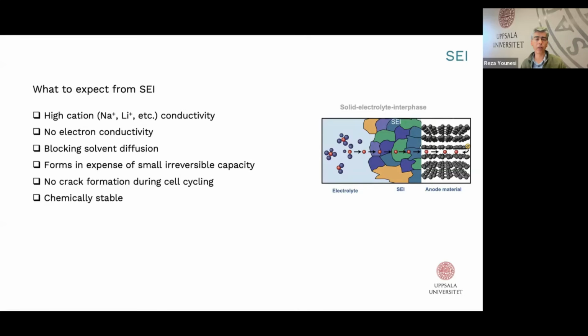It is expected that this SEI remains intact, with no decomposition over the lifetime of the battery at different conditions, temperatures, and cycling rates. Because if the SEI decomposes, a new layer forms at the expense of charge and electrolyte consumption, leading to aging and capacity fading. Ideally, we form SEI at the factory during the first few formation cycles with very little irreversible capacity, and that SEI remains stable and intact over the lifetime of the battery.